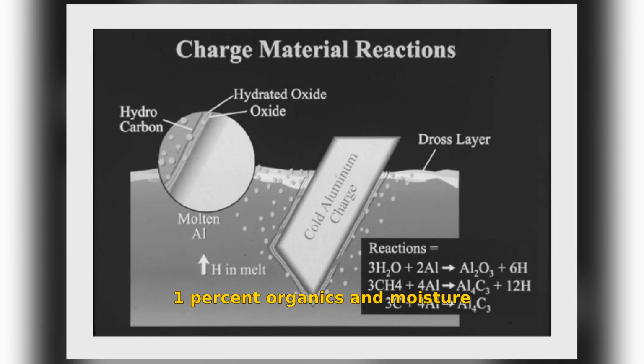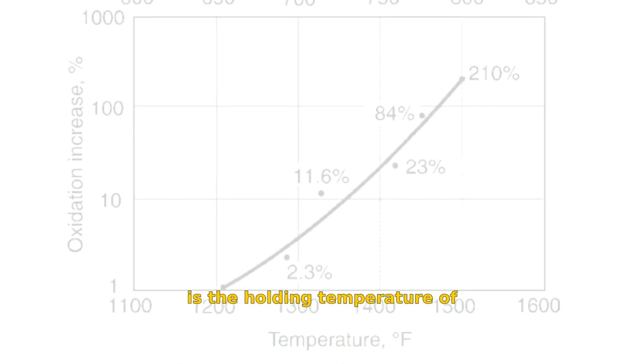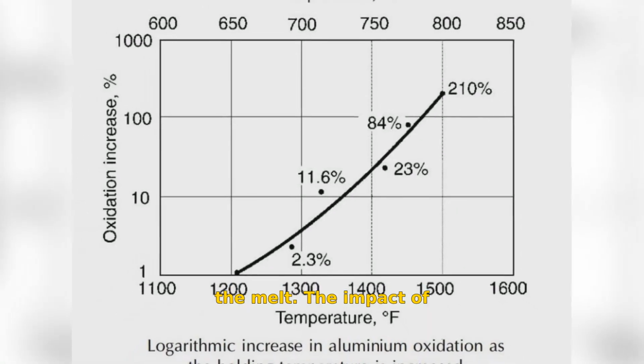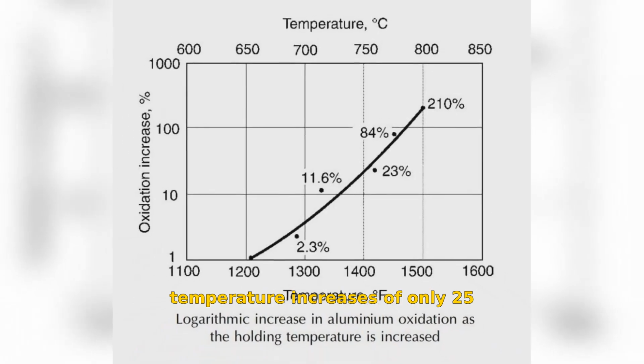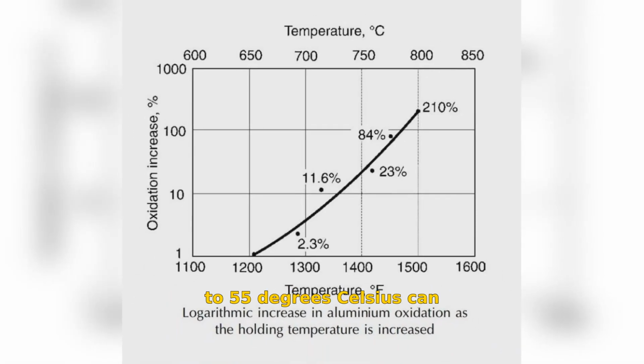For every 1% organics and moisture, 2% melt loss will result. Charging turnings, borings, and machining chips results in as much as 10 to 15% dross formation. An important factor is the holding temperature of the melt. The impact of temperature increases of only 25 to 55 degrees Celsius can be quite significant.